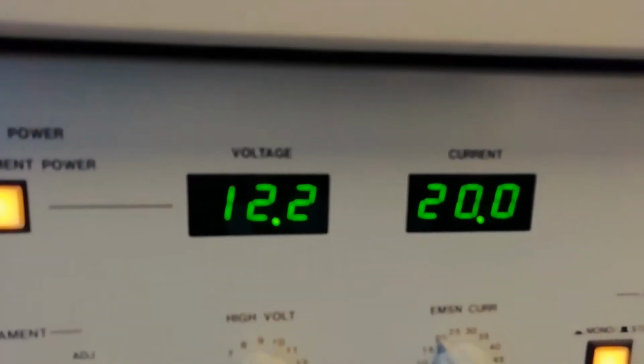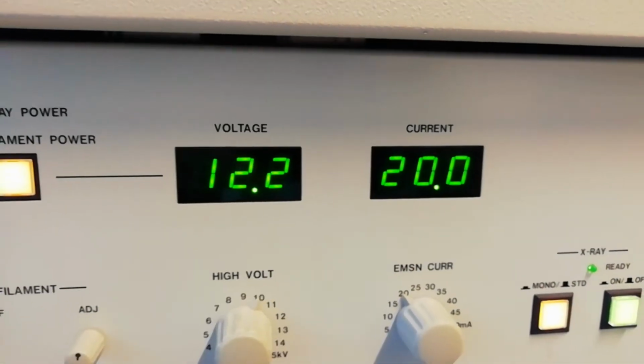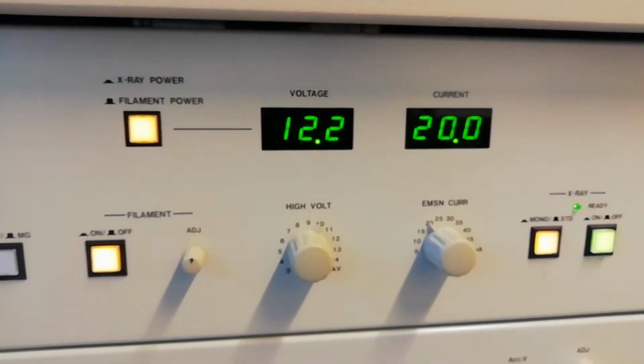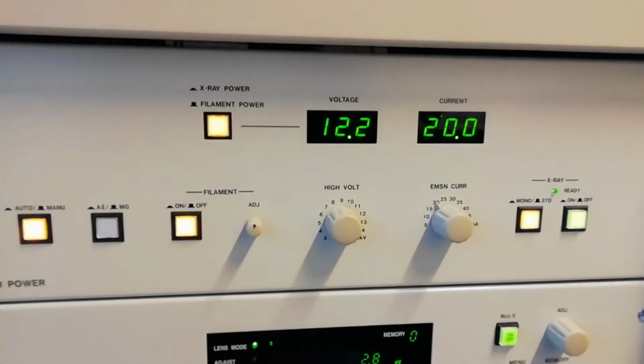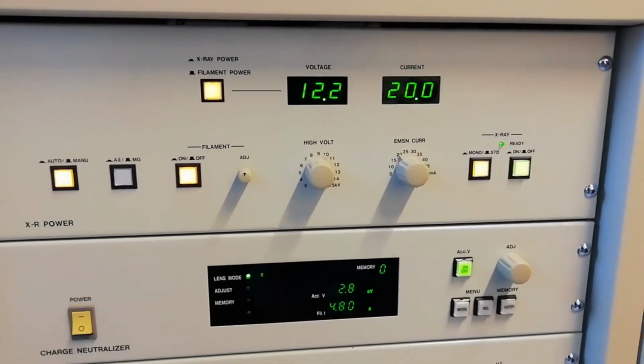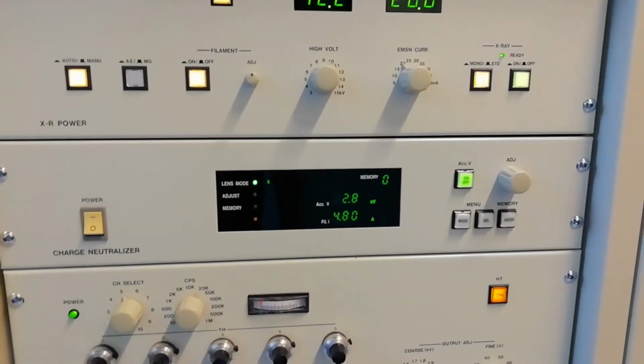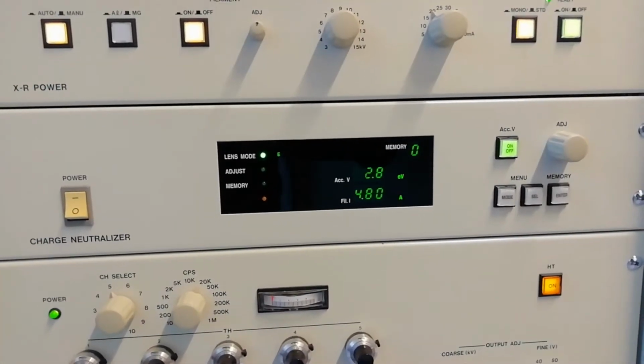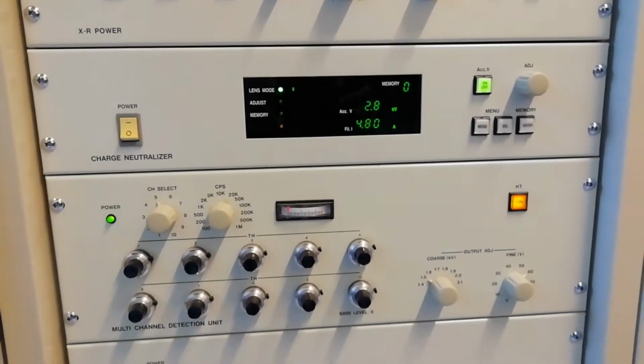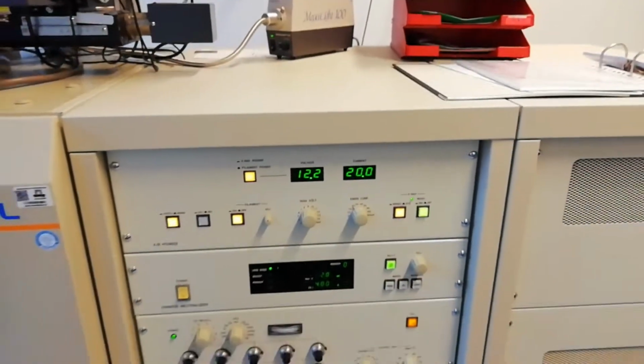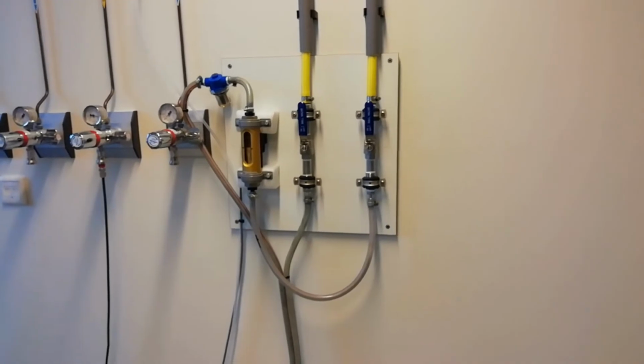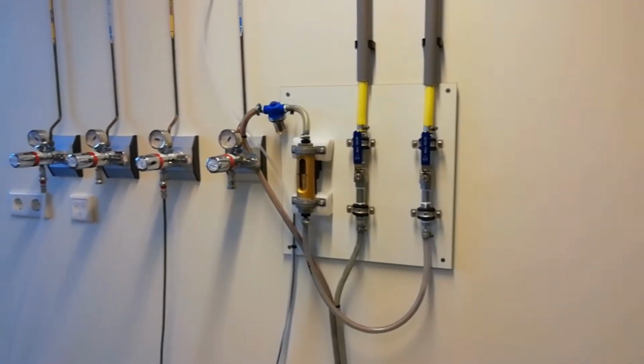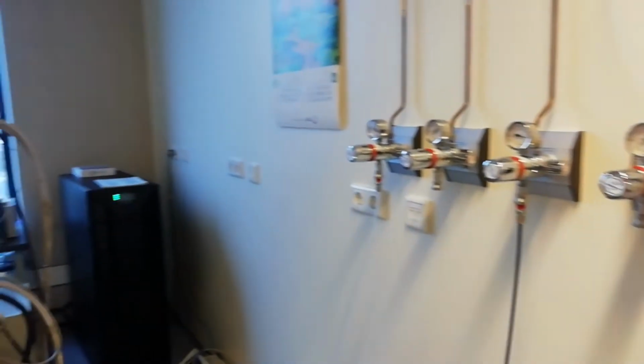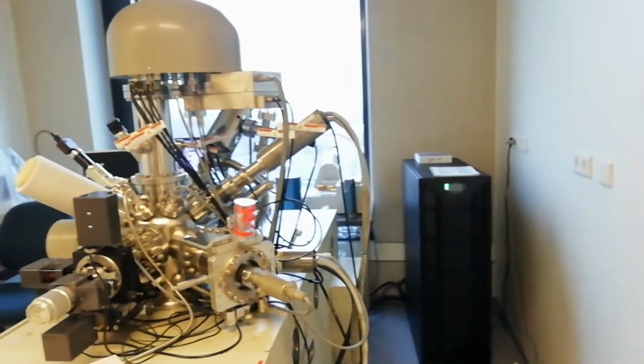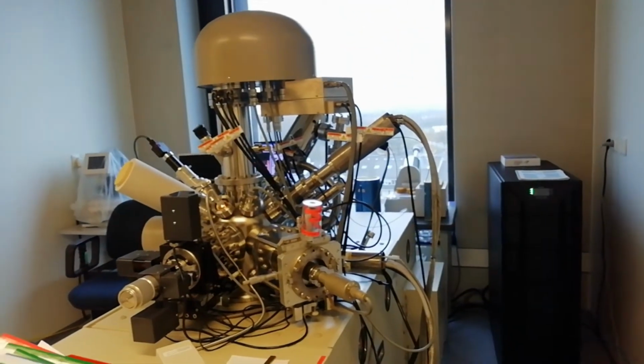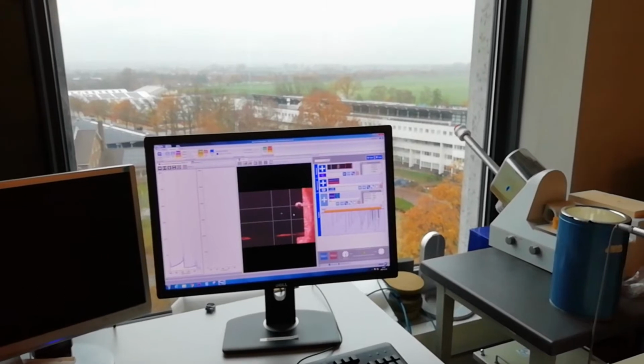The spectra were obtained under ultra-high vacuum, UHV, conditions using monochromatic aluminium K-alpha X-ray radiation at 12 kV and 20 mA, using an analyzer pass energy of 10 electron volts. Because of electrostatic charging in the positive direction on surfaces such as glass, charge compensation was used during the XPS scans with an accelerating voltage of 2.8 kilovolts and a filament current of 4.80 amperes.